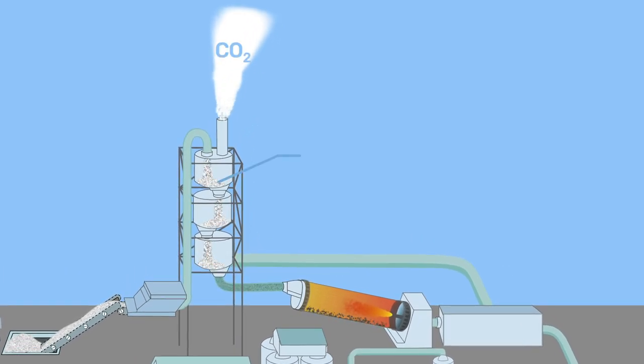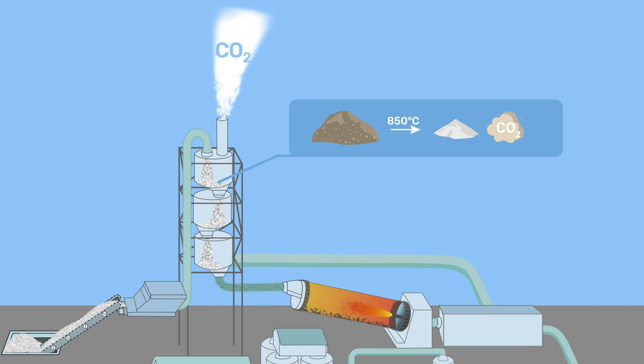In particular, the burning of limestone, which represents 80% of the raw materials, releases large amounts of CO2, accounting for 60% of total emissions. Because of this and of its large size, the cement industry accounts for 6 to 8% of anthropogenic CO2 emissions. This is why finding effective ways to reduce these emissions is a topic of intensive efforts both in industry and academia.